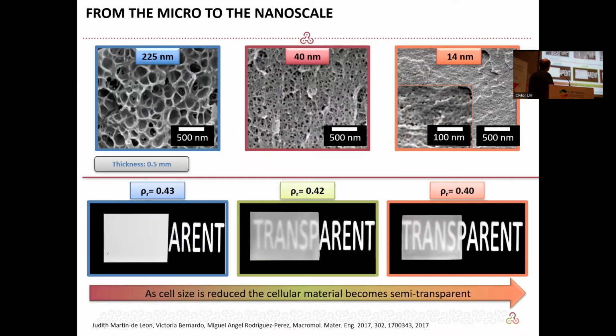So, sorry. Here we have 3 materials with the same relative density, so same amount of gas, more or less. Let's say this is 60% gas. This is relative density, so this is the solid fraction. Gas fraction would be 1 minus this. So we have more or less the same gas fraction. Different cell sizes, the same thickness. Thickness of these materials is very small, around 0.5 millimeters. You see, when the cell size is not too small, it's 220 nanometers, which is very small in comparison with commercial materials, we have opaque material, even for this very small thickness, due to scattering. We have scattering in this material, not translucent at all. But when we move to much smaller cells, you see we have some transparency in the material.